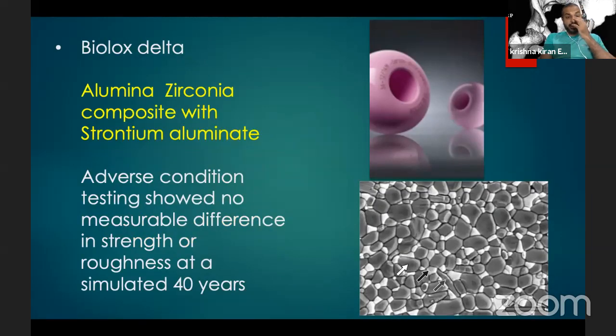But the Biolox Delta, which is an alumina zirconia composite with strontium aluminate, has been shown to have good outcomes in the laboratory. Adverse condition testing showed no measurable difference in strength or roughness at a simulated 40 years. That is, they put a lot of debris into the articulation and moved it through several millions of cycles and found that this articulation showed very good wear properties. It has also been shown to have very good fracture resistance, so the risk of fracture is lower.